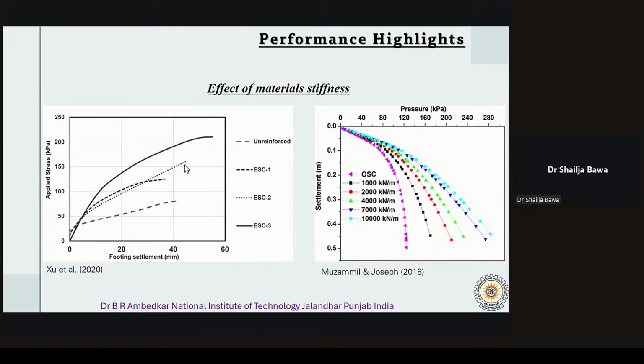So here ESC3, it is with the stiffest material, it can resist much higher stress with much less settlement. So this clearly shows that higher encasement stiffness leads to better load transfer and improved stability. Now turning to the graph on the right. This plot shows settlement versus applied pressure for different encasement stiffness levels in floating stone columns.